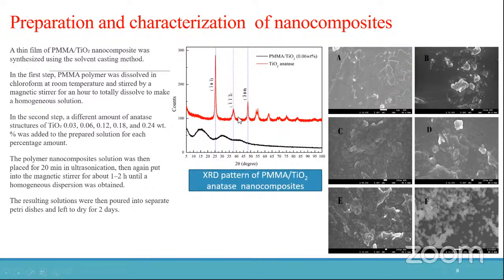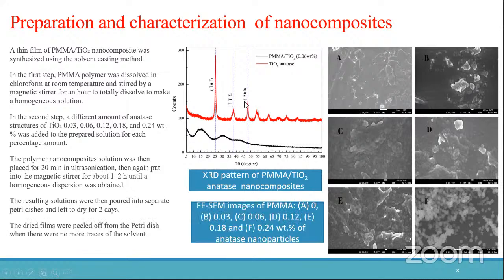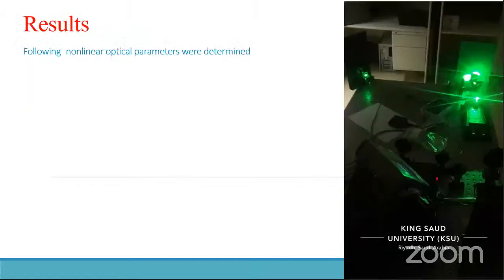So here you can see the XRD pattern of titanium dioxide and the polymer. You can see here in the polymer a very little peak of 101 of titanium dioxide is appearing, which shows that the nanoparticles are present in the sample in a very low quantity. So here you can see the SEM of all 6 samples, and in figure F we can see the distribution of these samples, because this sample has a very high concentration of titanium dioxide nanoparticles.